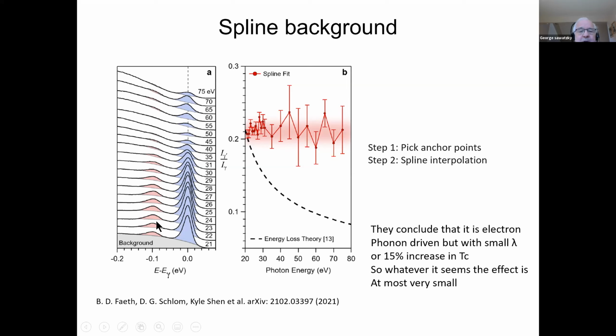But what they then find is that the intensity ratio between these two, between the satellite and the main peak, of course tells you something about the electron-phonon coupling, lambda.